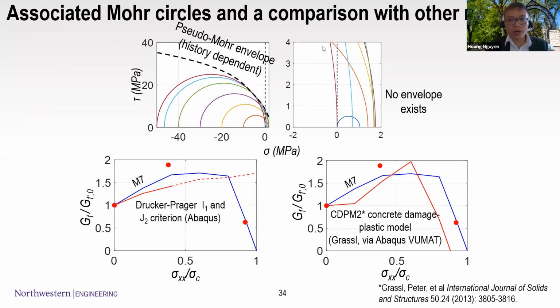So another point we should note is if you use the Mohr circle to plot the stress state at the crack tip. If we denote tau as the difference between sigma 1 and sigma 3, which is the stress causing the fracture to occur, and then the crack-parallel stress, you can see that there's no envelope that exists here when we zoom in on the image.